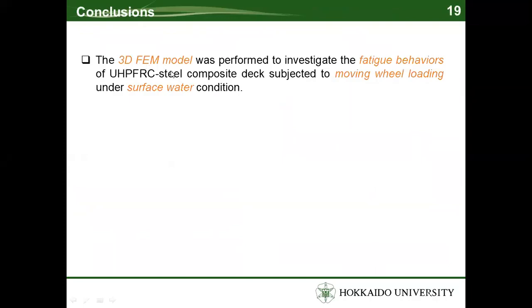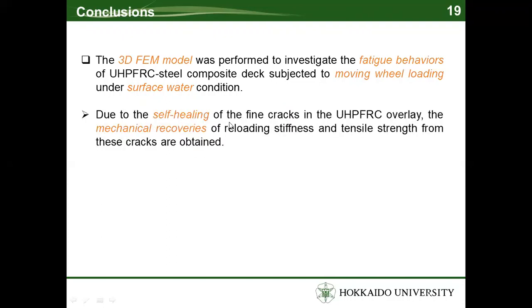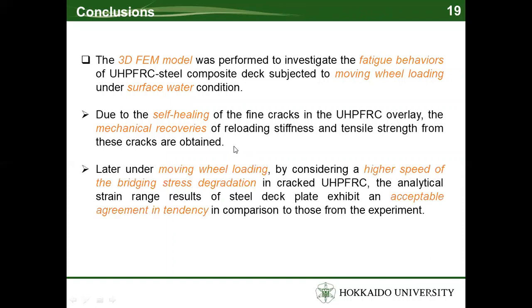Conclusion. The 3D FEM models were performed to investigate the fatigue behavior of UHPFRC steel composite bridge deck subjected to moving wheel loading under surface water conditions. Due to the self-healing of the fine cracks in the UHPFRC overlay, the mechanical recovery of reloading stiffness and tensile strength from the cracks is obtained. Later, under moving wheel loading, by considering a higher speed of bridging stress degradation in cracked UHPFRC, the analytical strain range result of the steel deck plate exhibits an acceptable agreement in tendency in comparison to those from the experiment.